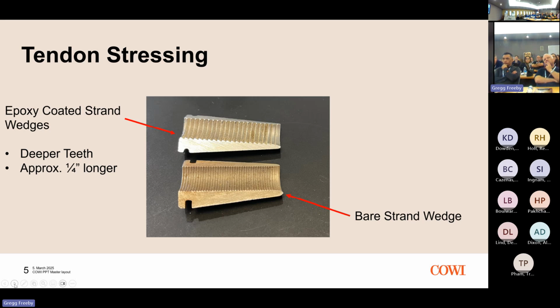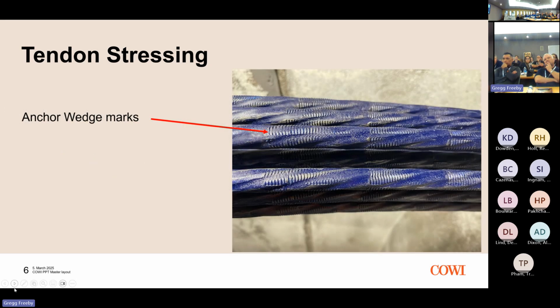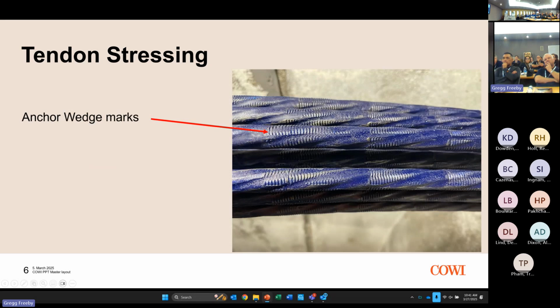And I've got some photos later about some where we removed some of the epoxy to verify it. You'll see some strand tails out there on site. So this is what the wedge anchor marks look like. One thing you'll notice as you look at the strand tail, when we go to 20%, you can see at the very end, the indentation of the wedges into the epoxy is not nearly what it is as you go down to where we were more at our full stressing force.